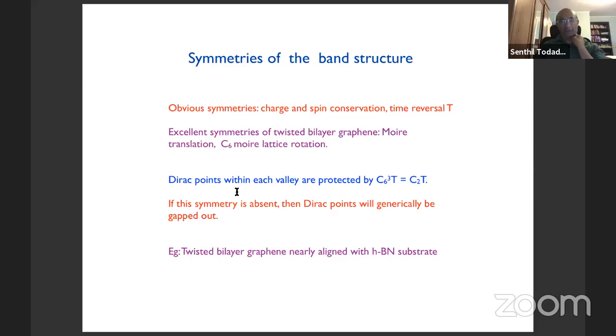Now, the Dirac points of twisted bilayer graphene within each valley are protected by a combination of these symmetries. They're protected by a C2T symmetry. And some of you who know graphene, ordinary monolayer graphene, will know that C2T is also the symmetry that protects the Dirac band touchings of monolayer graphene. So now in twisted bilayer graphene, if somehow you break C2T symmetry, then generically the Dirac points will be gapped out.